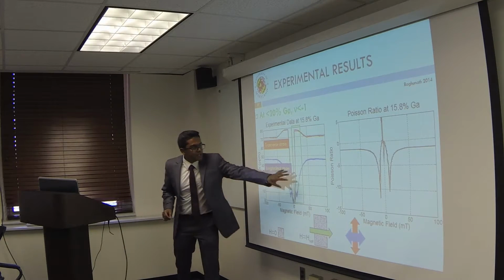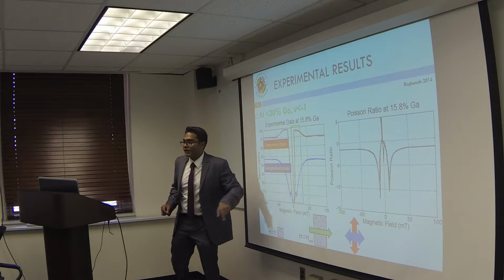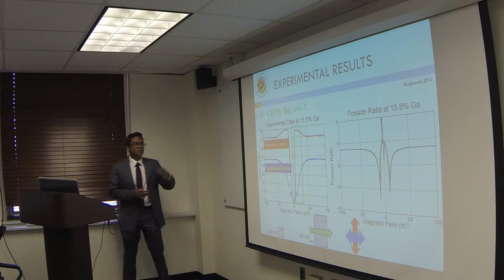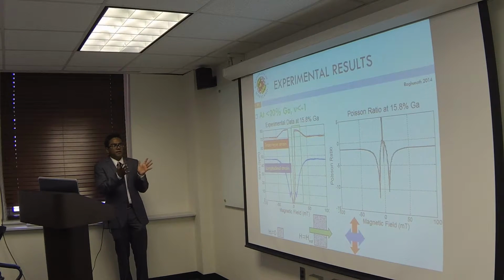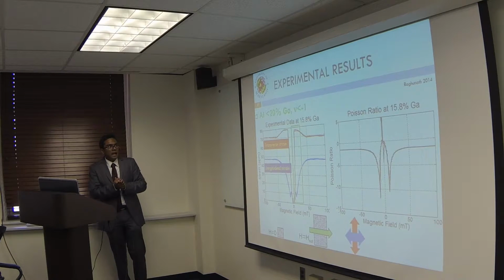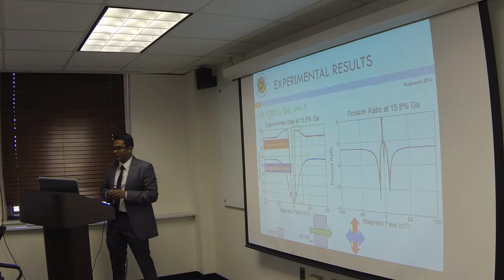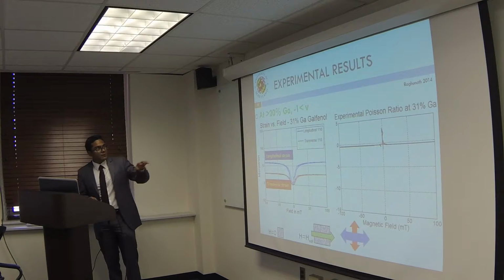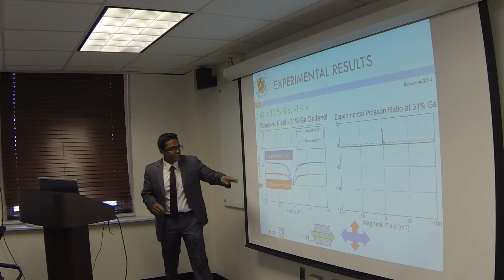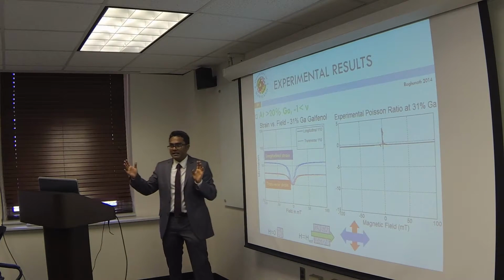So we will be discussing more about the non-monotonic increase in the strain values, and we were really intrigued by this because we weren't expecting to see this. And we see this only in samples with less than 20% gallium. In samples with greater than 20% gallium, we see monotonic increase and we reach magnetic saturation.